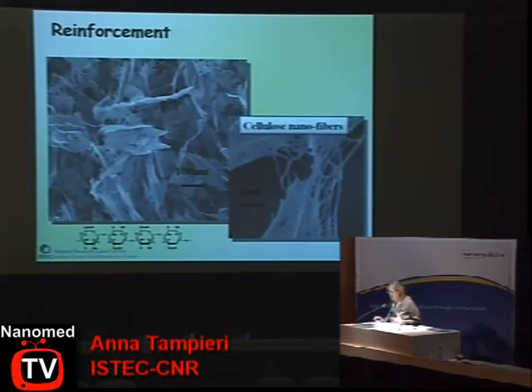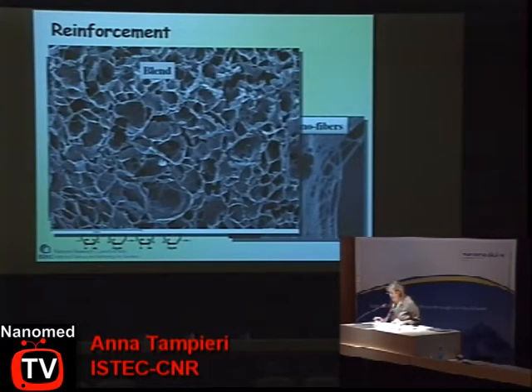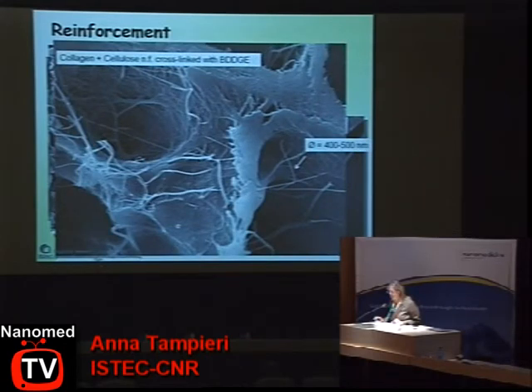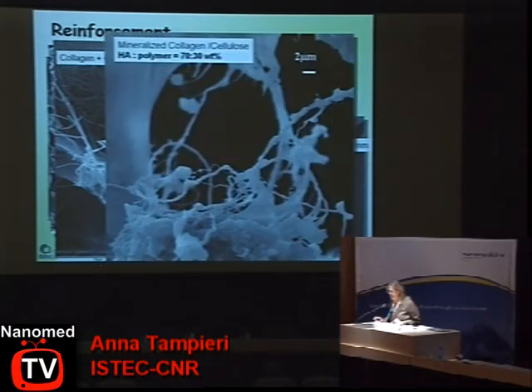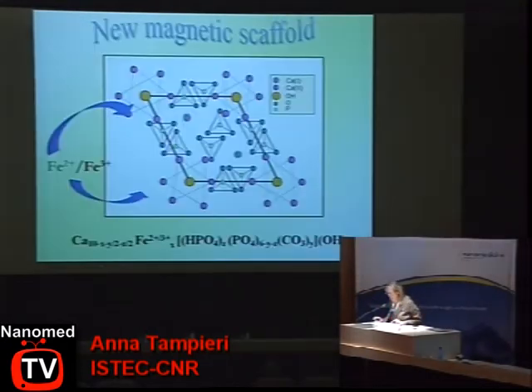One concern is the reinforcement of such a kind of scaffold to be able to repair defects larger than focal defects. So we have also tried a new development of the biohybrid scaffold, a collagen-hydroxyapatite biohybrid scaffold reinforced with cellulose nanofibers produced by bacteria. And this is the blend. And as you can see, this is the reinforced composite, which is more stable, and its degradation has a lower kinetic. And this is a detail of the mineralized scaffold.